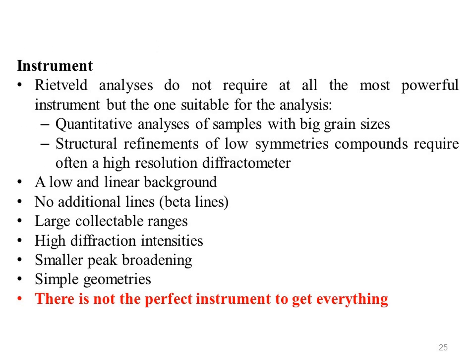Rietveld analysis does not require at all the most powerful instrument, but the one suitable for the analysis. Quantitative analysis of samples with big grain size, metal, high crystal symmetries require a diffracting volume of statistical significance, large sampling volume, large beam with not too low divergence, a medium to low resolution diffractometer. Structural refinements of low symmetries compounds, monoclinic, triclinic, often require a high resolution diffractometer.